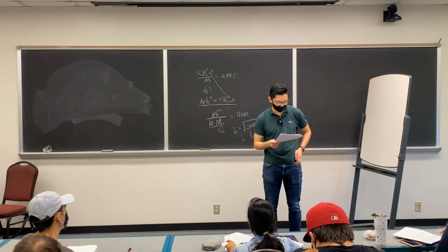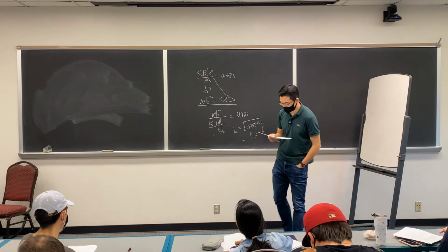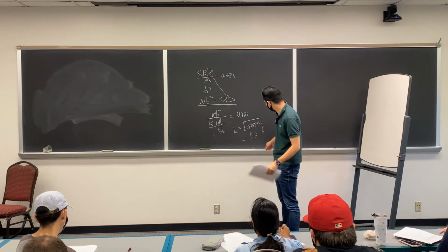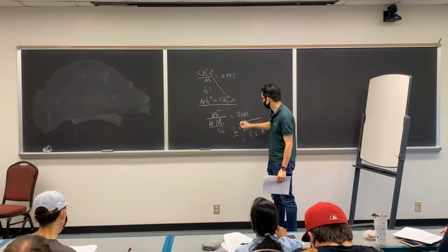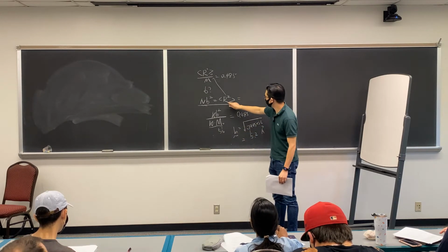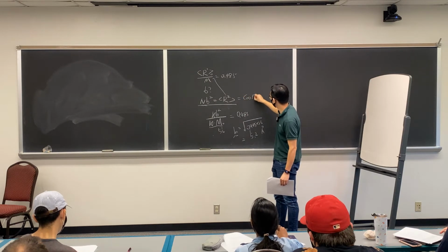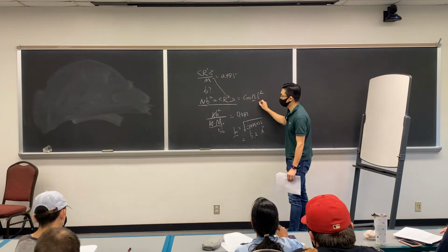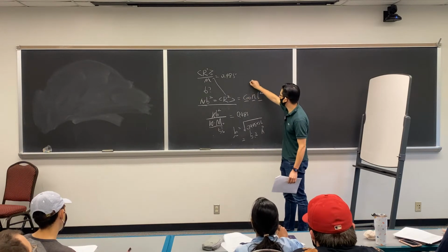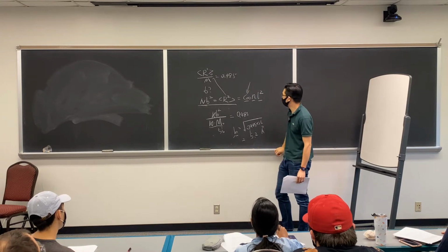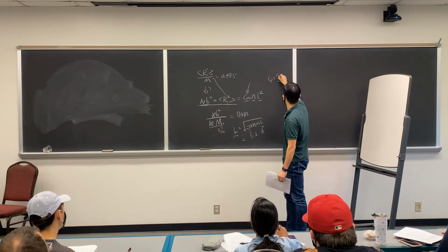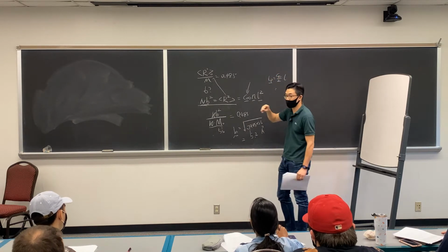In the next part, it asks you what the persistence length is, and that could be a confusing part. So how do we get persistence length if we know, for example, the b value? It's not that hard. Again, our end-to-end distance squared will be equal to C infinity n l squared: number of bonds, bond length, and characteristic ratio. We can get the characteristic ratio based on N b squared, and we can use l_p equals half of C infinity l to get the l_p value.